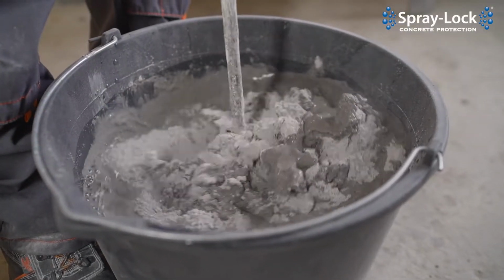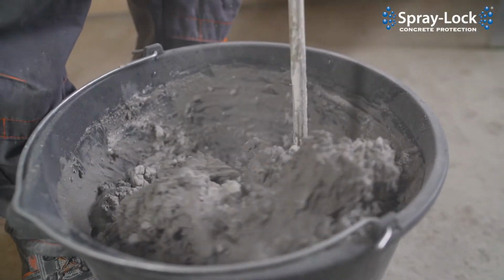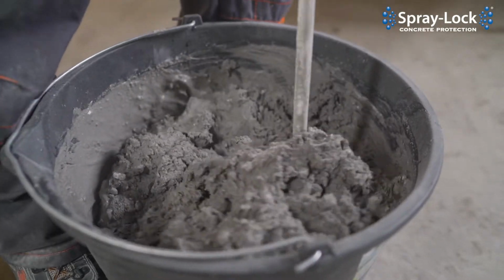So basically, the way that you calculate water to cementitious ratio, you take the pounds of water, or kilograms, or whatever unit of measure you're using, just the mass or weight of the water per cubic meter or cubic yard, here in this country, cubic yard. And you divide that by your total cementitious content in pounds or kilograms. Don't switch the units between water and cementitious. That includes your cement, your pozzolans, your supplementaries, your ashes and other things.